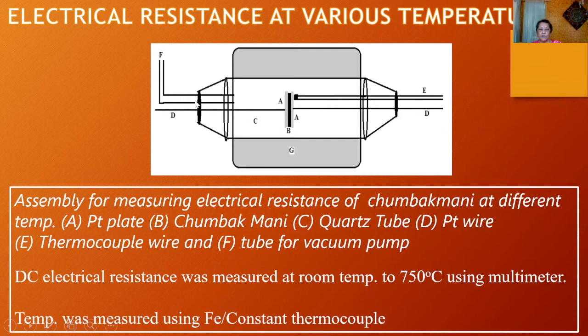So this is the tube to create the vacuum. And DC electrical resistance was measured at room temperature to 750 using multimeters, and temperature was measured with a thermocouple that I have told you about here. So that was electrical resistance at various temperatures.